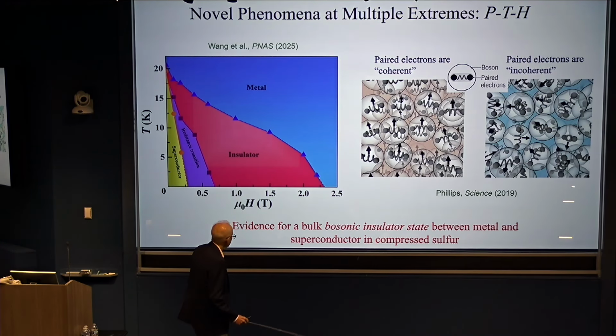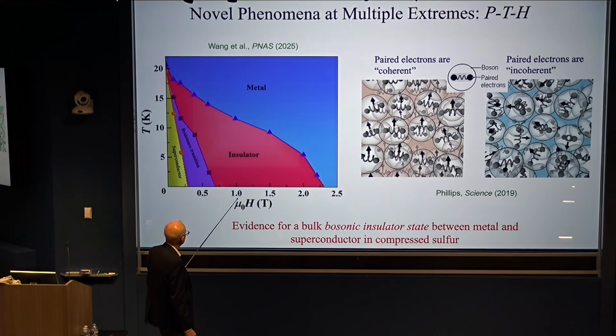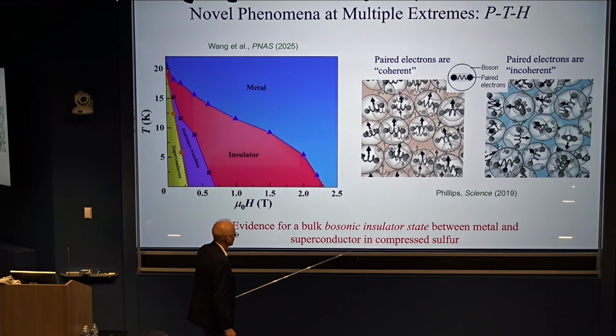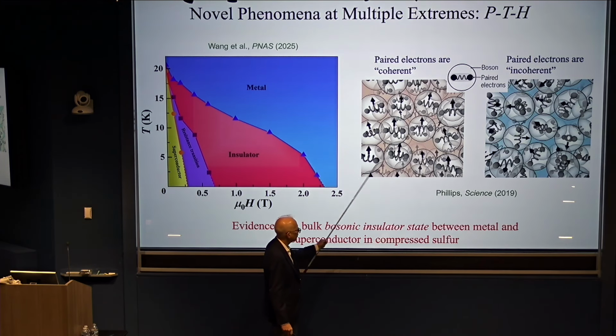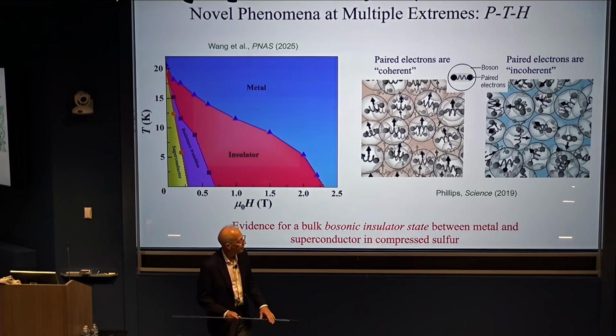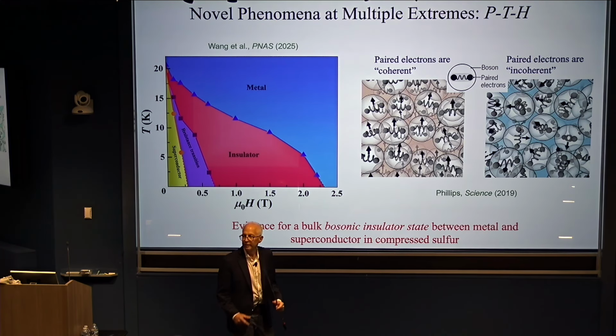That led him to create this phase diagram, which is a new kind of phase diagram. It's temperature versus magnetic field. Here's the metallic state, and here's the resistive state. But in this intermediate regime, we believe this is something in between the two. It's a bosonic state where you have bosons, Cooper pairs, but they're not coherent. So it's not superconductivity, because the bosons aren't coherent. This kind of thing has been seen or proposed in disordered materials and thin films, and we believe this is the first example of this interesting state of matter in a bulk material, because this is a bulk, very simple material, simply sulfur.